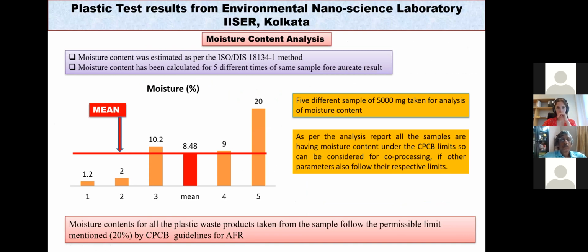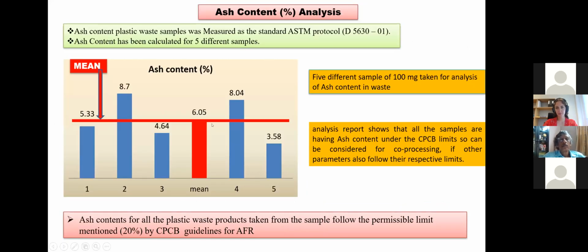The 5 different samples have been taken for testing with the weight of 5 grams each. So the mean value of the moisture content is 8.48%, which is under the CPCB guideline limit of 20%. So that can be considered as an AFR for co-processing.